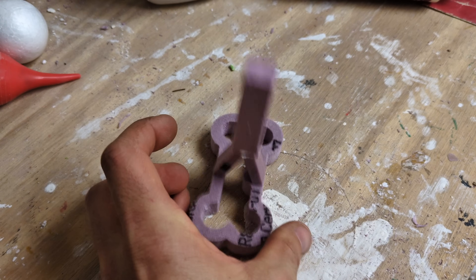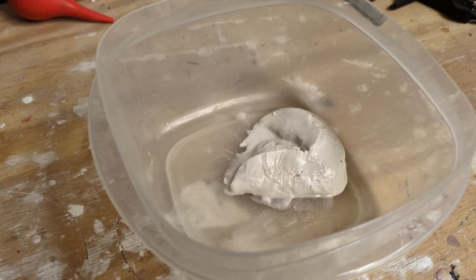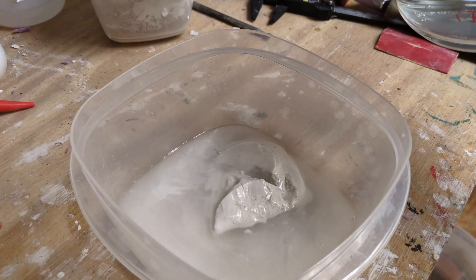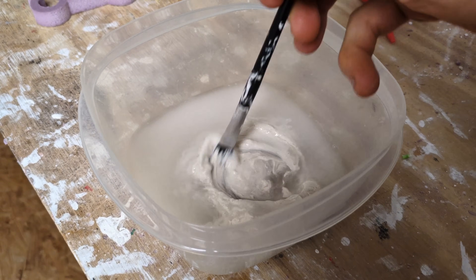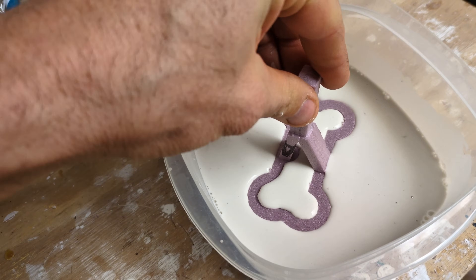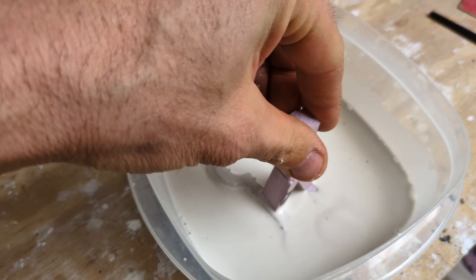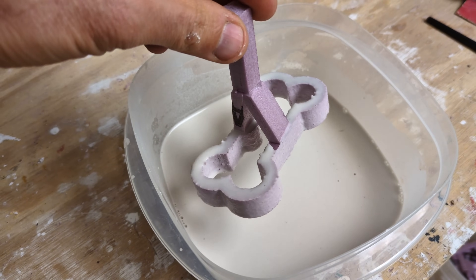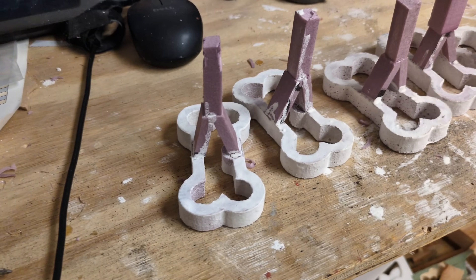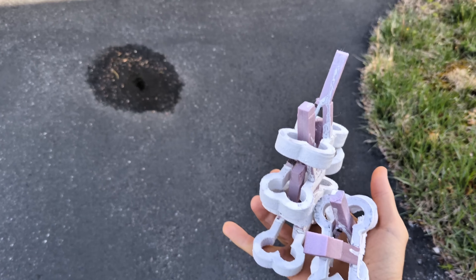After 24 hours and the glue has hardened up, I then apply a watered-out mix of sheetrock drywall mud to the pattern. In this clip the drywall mud is a little bit too runny — I actually added more drywall mud to the water after this clip because it was just too thin. You don't want it this thin, but you still want it kind of thin. And this is what they all look like after 24 hours of drying.